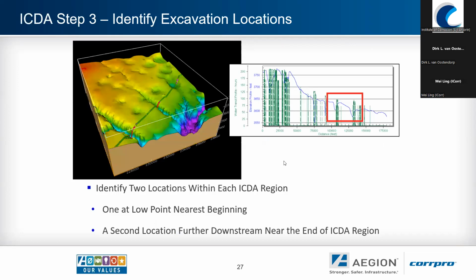Taking the data one step further and projecting that out onto the topography of the pipeline, we can actually see where this was in space. So again, the graph on the right-hand side is the overall length of it. The snippet in the red box is actually what's shown there in 3D, to where we can actually see the flow and where the water is getting caught on the uphill rises on the pipeline coming out of some of these depression points on the pipeline. It's somewhat counterintuitive in that sense, that those are the areas where the highest amount of water would be found, as far as the number of hours that the water is staying there.